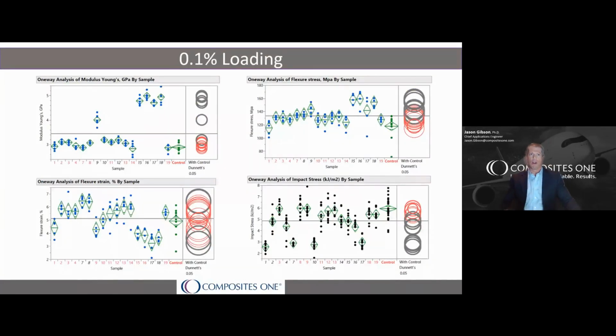So I'm showing 4 different graphs on this slide. All 4 are for the 0.1% loading. These are the flexural modulus, the stress, and the strain, and that bottom right graph are the impact results. You'll notice each graph has a bunch of colored circles on the right. These tell us which results are statistically significant, which simply means that the differences in the samples tested and the control are significant enough that we can be confident that there's a difference.